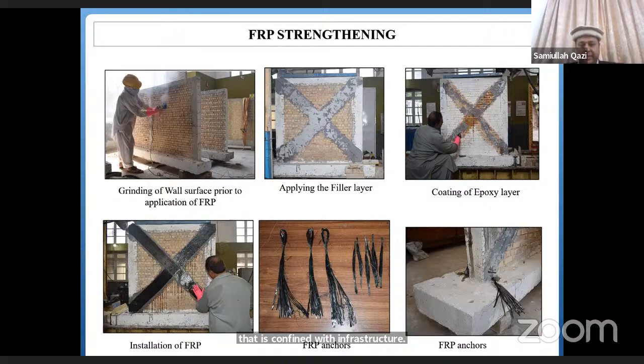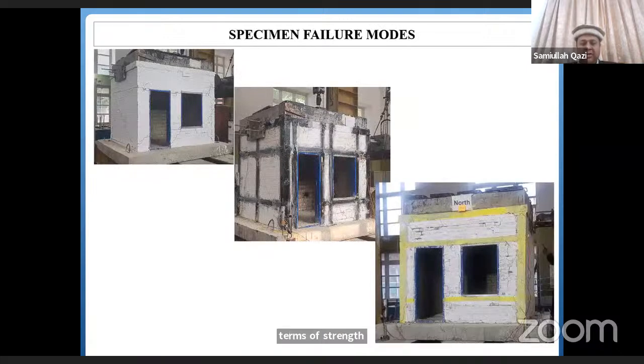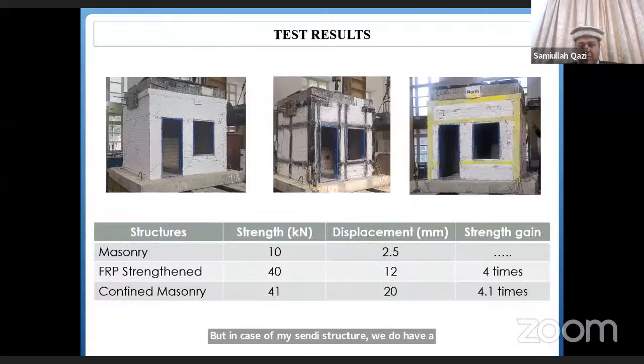So in terms of strength, in case of masonry, we have a 10 kilonewton lateral strength, whereas in case of FRP and confined masonry, we gain almost identical results, that is 40 kilonewton and 41 kilonewton. So it improved the capacity of a masonry structure almost 4 times. But in case of confined masonry structure, we do have a higher amount of displacement. We call it normally, from an engineering point of view, ductility. So confined masonry structure has gain in strength and also ductility. But in case of FRP structure, we have achieved the same amount of strength, and in terms of ductility, it is at a much higher level with respect to masonry.